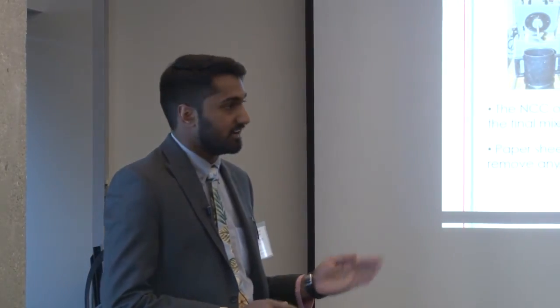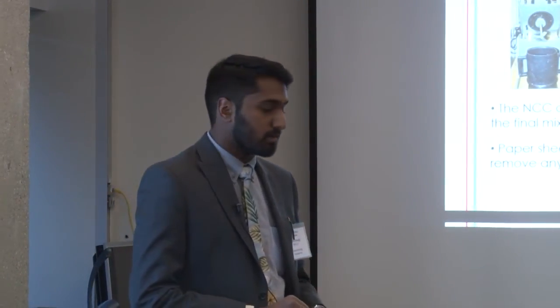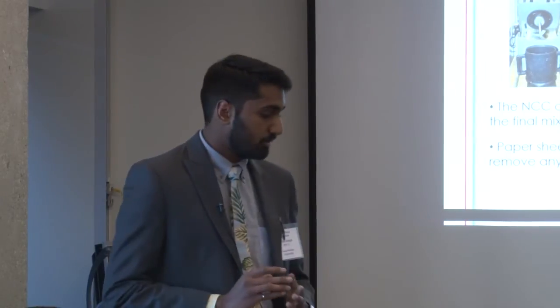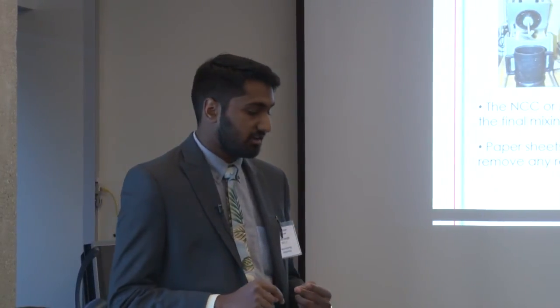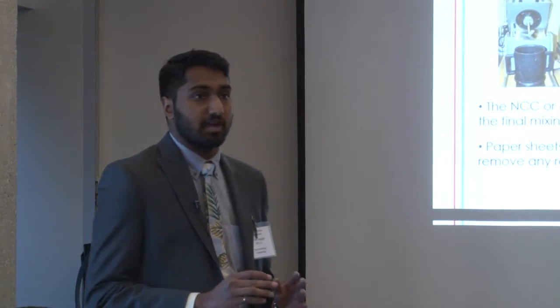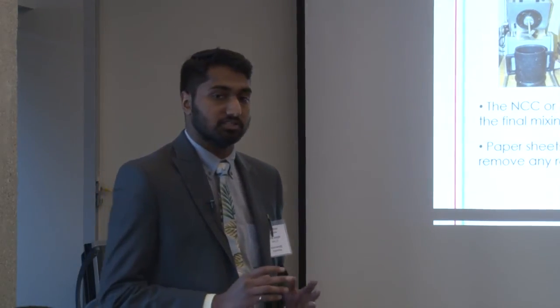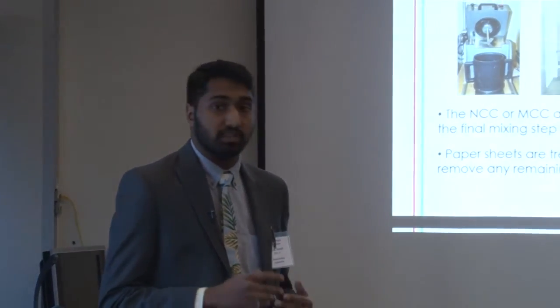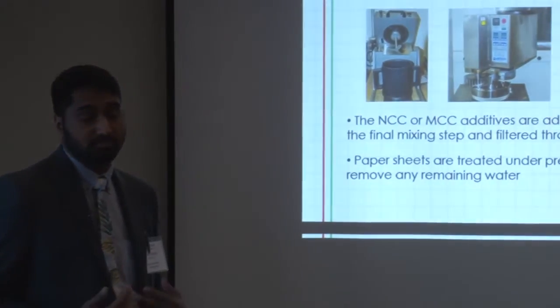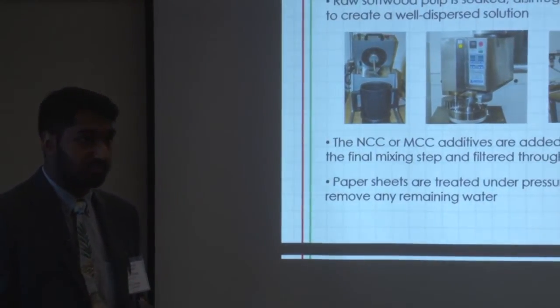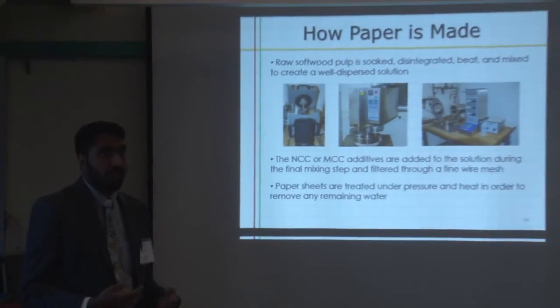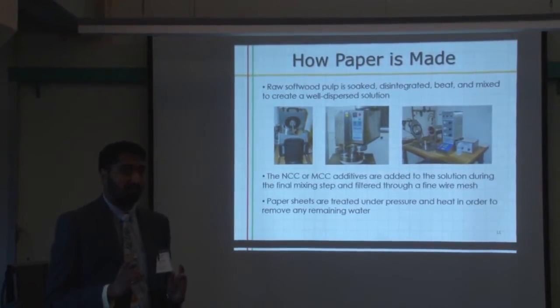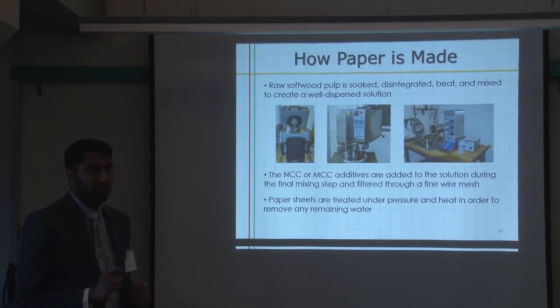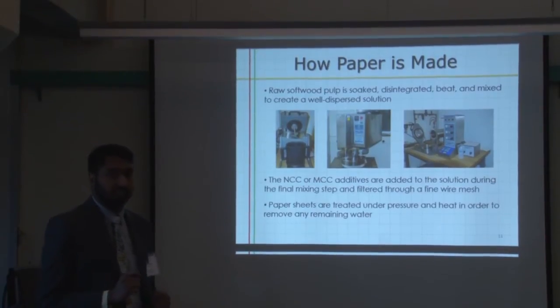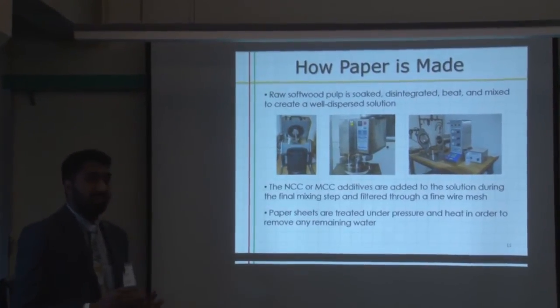There, we had access to their TAPPI standard laboratory-grade equipment where we were able to take raw softwood pulp, soak, disintegrate, beat, and mix it to create a well-dispersed solution of cellulose fibers. Into this solution, we then added our NCC and our MCC. Once again, we redispersed it, created a homogeneous solution, and then we filtered it through a fine wire mesh. This creates a paper handsheet. This is then treated under high pressure and temperature to remove any remaining moisture.